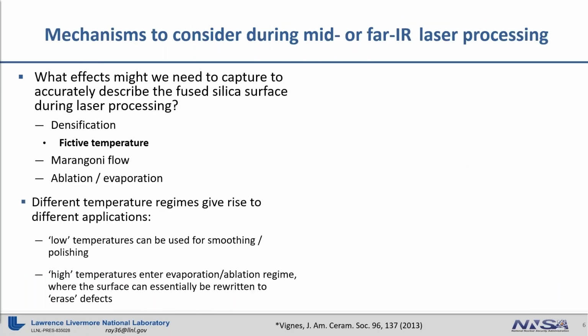But the question then is, what do we need to consider if we want to try to model this? We can break this laser material interaction into different regimes, basically governed by the temperature. So densification, and from that fictive temperature, I'm going to go into more detail on the next slide. But that's something that we will need to include. Marangoni flow. As your fused silica gets hot, the viscosity drops, at which point you might have surface tension driven flow, basically glass reflow. That's a physics phenomenon that you might want to include in your model. Or if we take it to the other regime, high temperature ablation or evaporation is something else that you might want to include in a model to capture all of the physics.